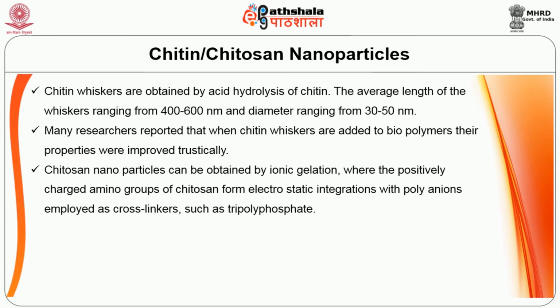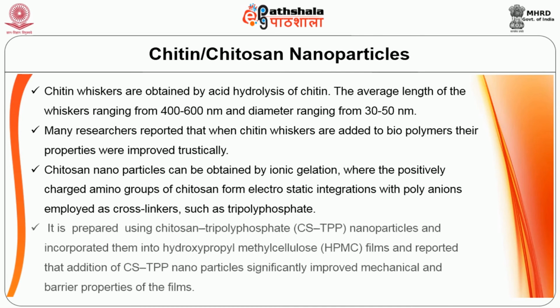Chitosan nanoparticles can be obtained by ionic gelation, where the positively charged amino groups of chitosan form electrostatic interactions with polyanions employed as crosslinkers, such as tripolyphosphate. Researchers prepared chitosan tripolyphosphate nanoparticles and incorporated them into hydroxypropyl methylcellulose films, and reported that the addition of CS-TPP nanoparticles significantly improved the mechanical and barrier properties of the film.